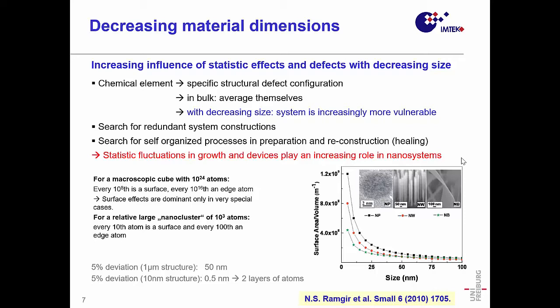And another idea to show how small we are going and what might be the problem we are facing: simply think you want to do a lithography step and you have a deviation of 5%. If you do it on a micrometer scale, then 50 nanometers is not what you care for, but if you do it with something like a 10 nanometer structure, then 5% of a deviation means 0.5 nanometers, and that means one atom on each side.